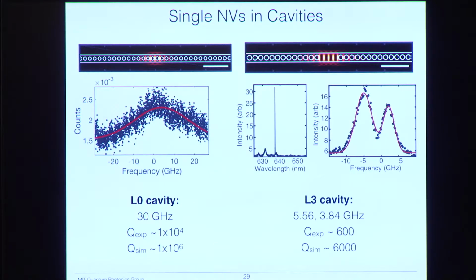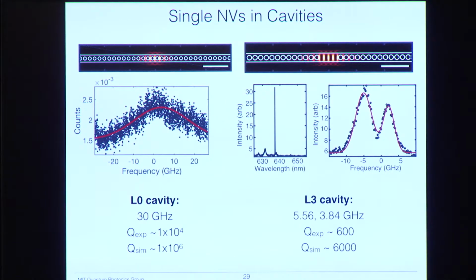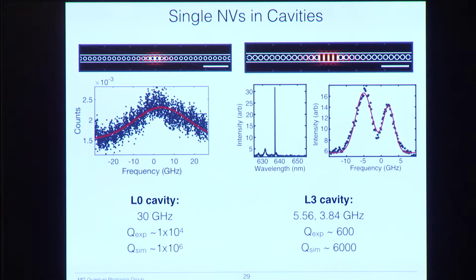width. Unfortunately, this gets even worse with cavities, because in cavities, the NV center is even closer to surfaces. So for an optimally placed NV center in what we call an L0 cavity, it would be within 30 nanometers of the hole surfaces right next to it.